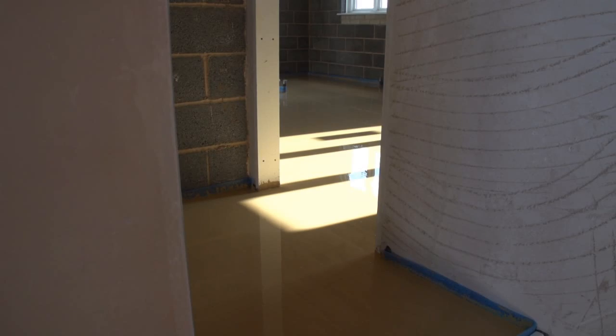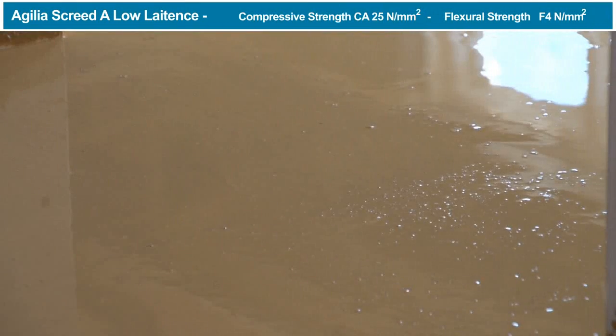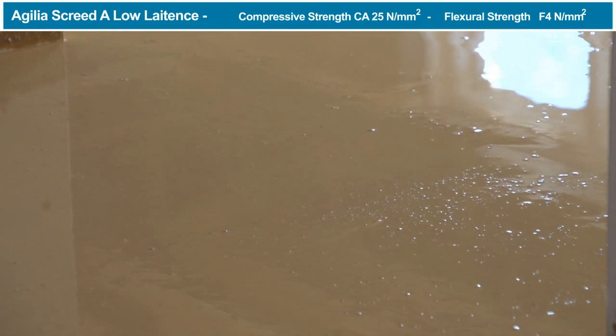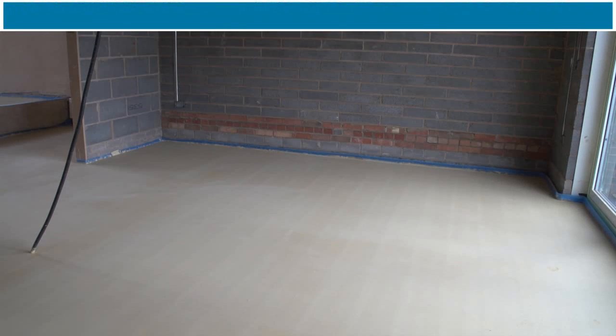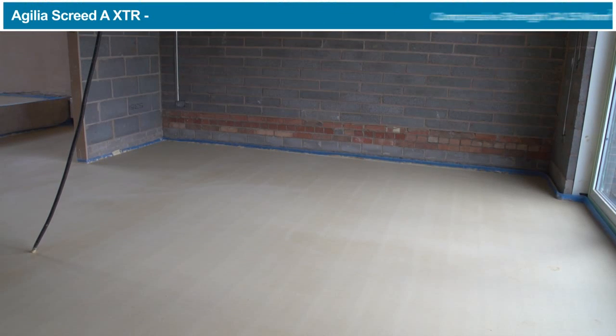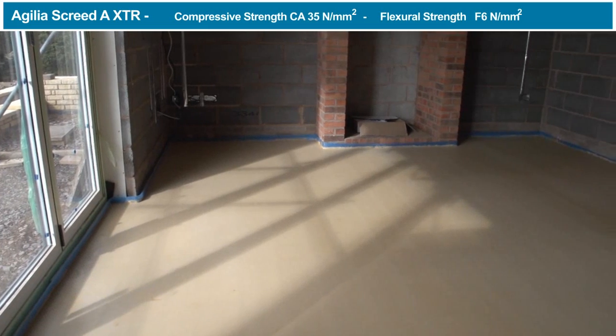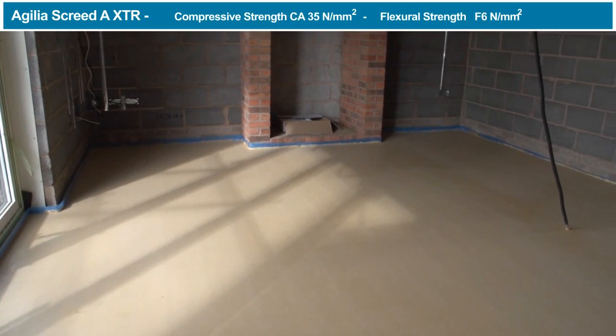Unlike sand cement screeds, Agilia Screed A forms its own curing membrane prior to setting. This removes the need and cost of the polythene sheet curing process. The screed will generate a minimum compressive strength of 25 newtons at 28 days. For higher point loadings, Agilia Screed A is available in XTR specification, achieving a 35 Newton compressive strength.